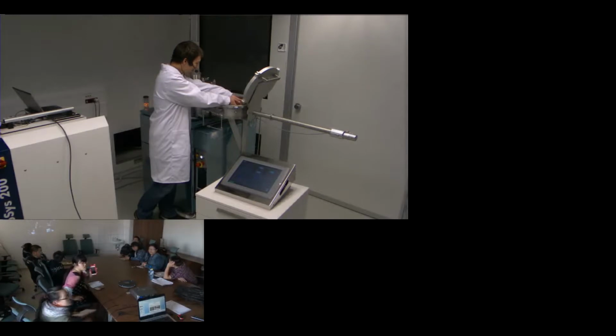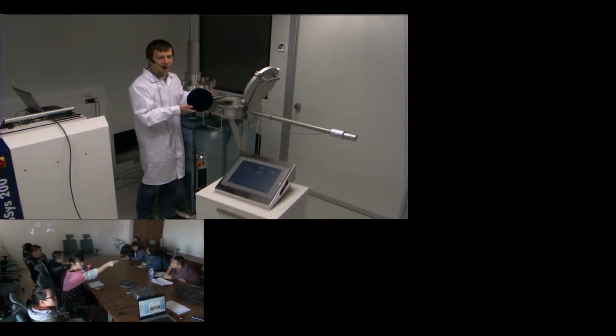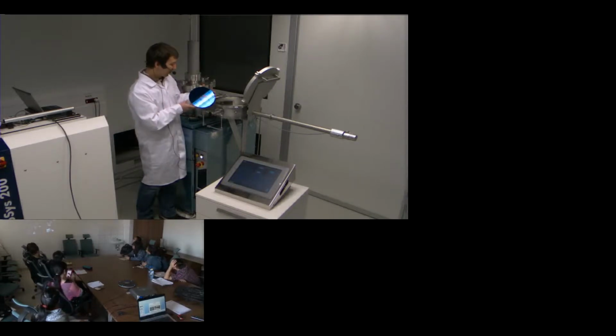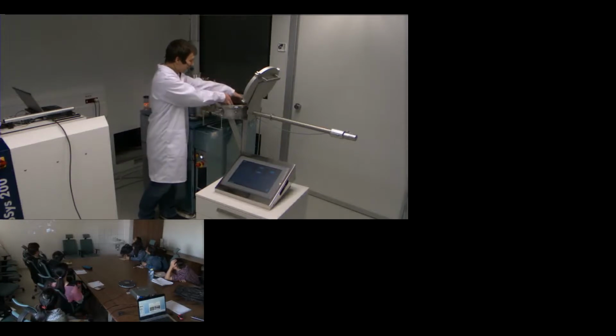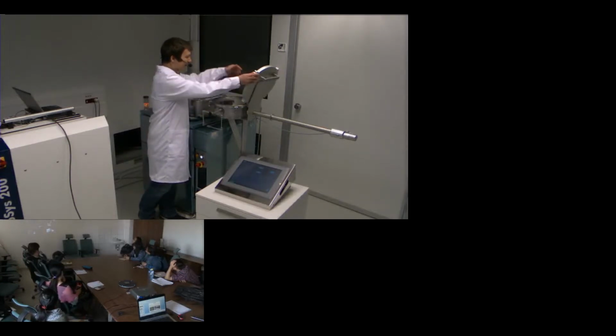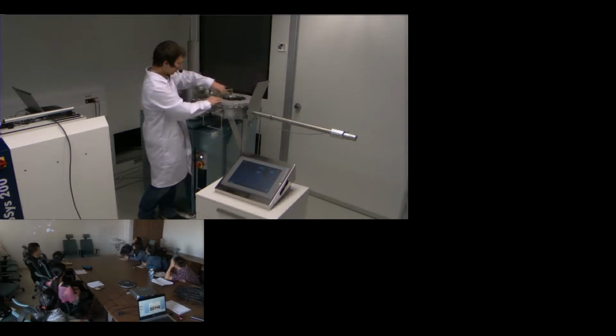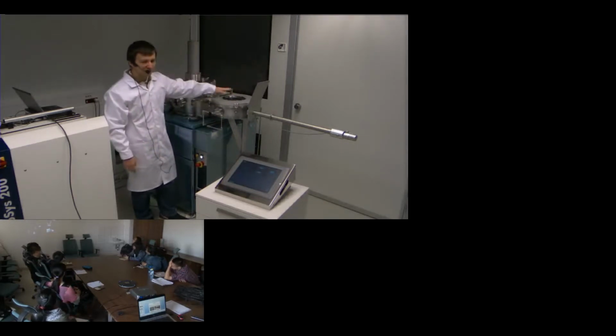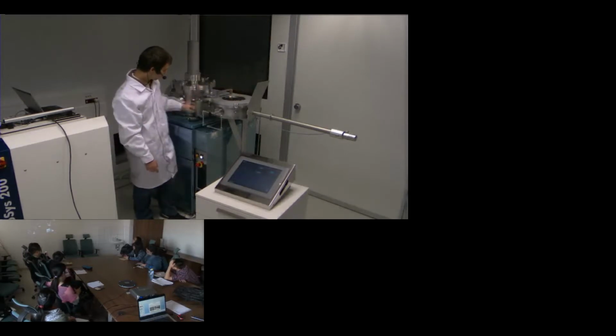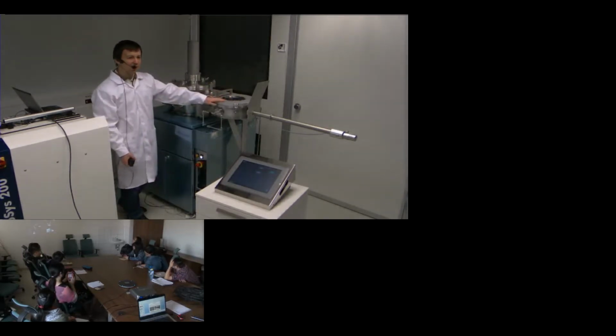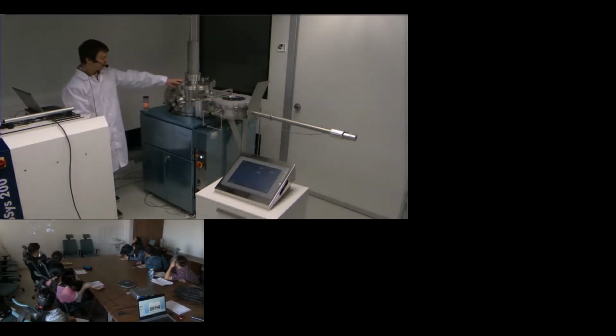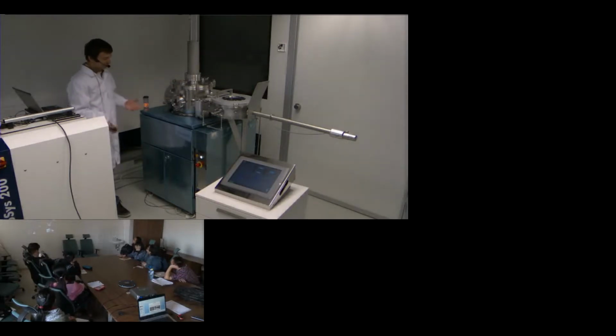In general I can show you. Here we have a typical substrate for materials deposition, like this silicon wafer, which I can put inside the chamber here. Then I can close the lid to the load lock. It is sealed with a Viton seal, and then we can evacuate it, so we have a vacuum inside. Later, our sample is transported to the second chamber, which is here. This is the reactor chamber, where the deposition process takes place.